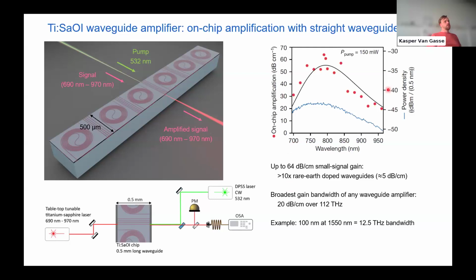So this is the result from that measurement. And what we can see is that we can get, this is expressed in dB per centimeter, so this is extrapolated from this measurement. What we can see is that in principle, our waveguide would give up to 64 dB per centimeter of small signal gain. And why are we interested in this?